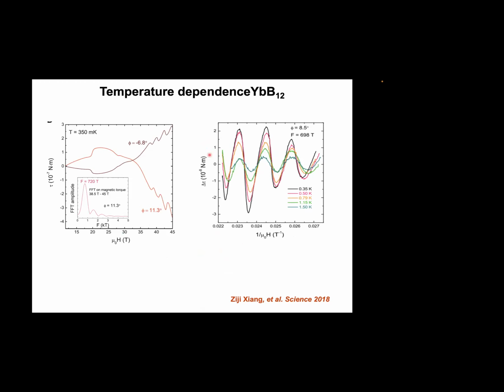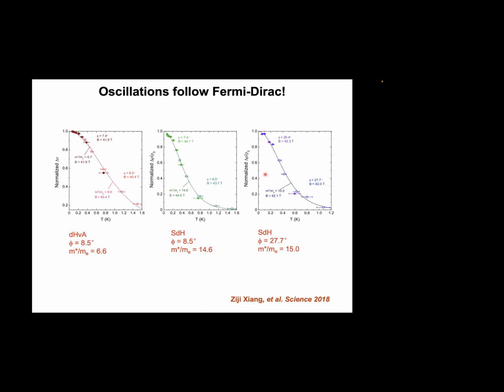And even more, we can start to look at the temperature dependence. This is the magnetization, and we look at how warming up the sample reduces the amplitude, which is nothing surprising. This is the behavior of a fermion. This is what we expected out of the Fermi-Dirac distribution. The temperature dependence, typically called the LK formula, is simply the derivative of the Fermi-Dirac distribution, and torque follows that trend, and resistivity also follows that trend.